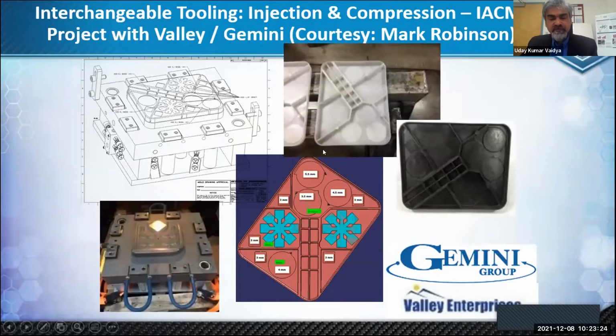Along the way, we also developed multiprocess tooling. So this particular tool is interesting in that it can be used in compression molding as well as injection molding, just by a few swaps of some hardware in the tool. This particular tool has extensively designed ribs of different natures. So one can get a range of coupons to evaluate fiber flow, fiber orientation, fiber distribution in the processes. So in a single tool, it can be used to evaluate multiple processes. And this was an IACMI project with Valley Enterprises in Michigan, a Gemini group.